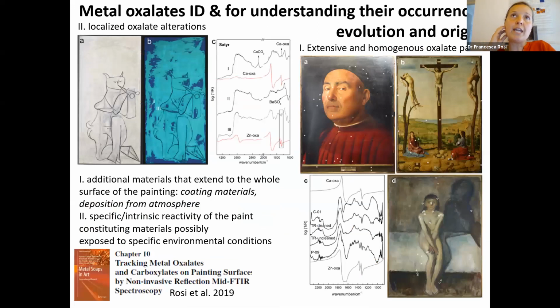The fact that we are working with a non-invasive technique also enables us to record, in principle, an infinite number of measuring points on the wall surface. This gives us the opportunity to further improve our knowledge about the occurrence and the evolution of the origin of the metal oxalate in painting. And thanks to our 20 years of activity, and we had the opportunity to investigate a lot of paintings, we can say that we found the two main situations regarding the distribution of metal oxalate.